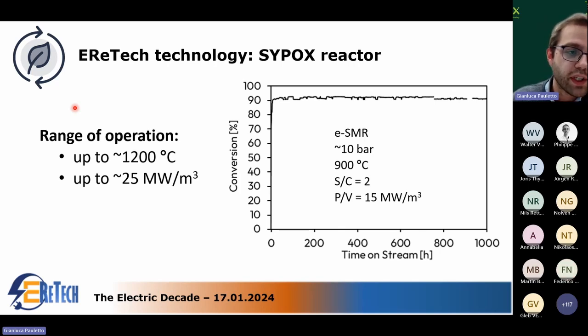What is the advantage, and what were we able to achieve before starting this? We saw that it's possible to reach a temperature as high as approximately 1,200 degrees Celsius. You can also achieve a huge intensification, meaning you are able to provide a lot of heat in a small volume. We will also talk later about the power to volume ratio, which can be as high as 25 megawatt per cubic meter. At the same time, we can see the performance of such a reactor when performing steam methane reforming. You can see here a plot of 1,000 hours of operation, a test at 10 bar, 900 degrees, steam to carbon 2. And you see that the conversion is very close to equilibrium and is also stable.